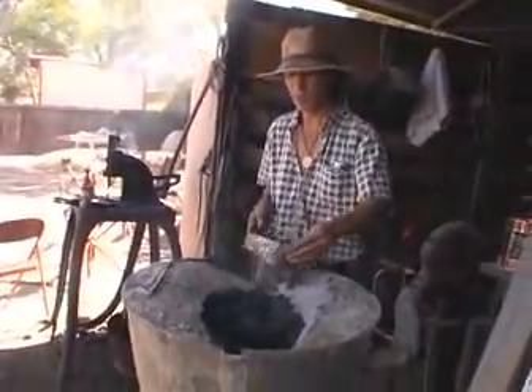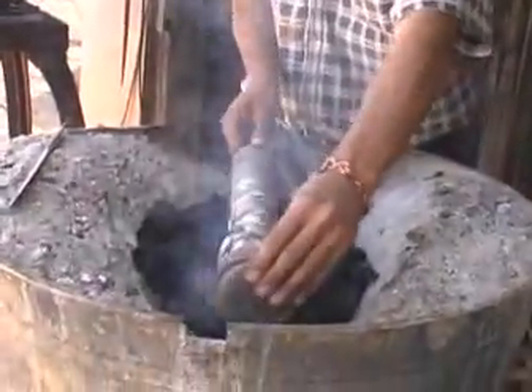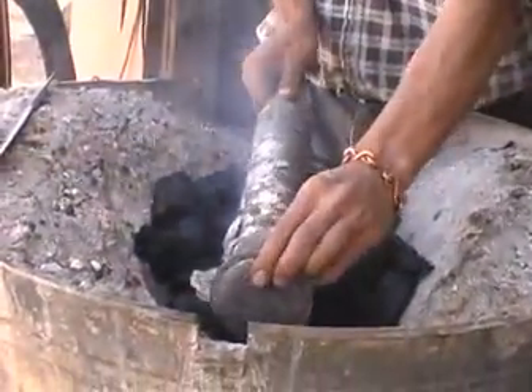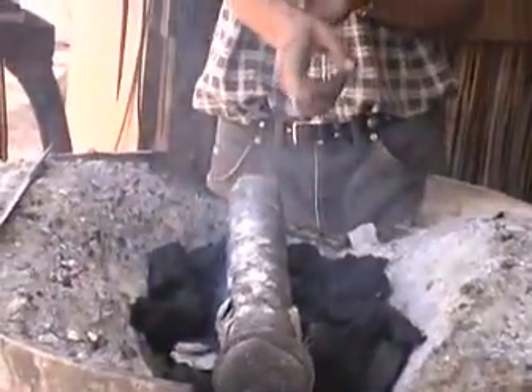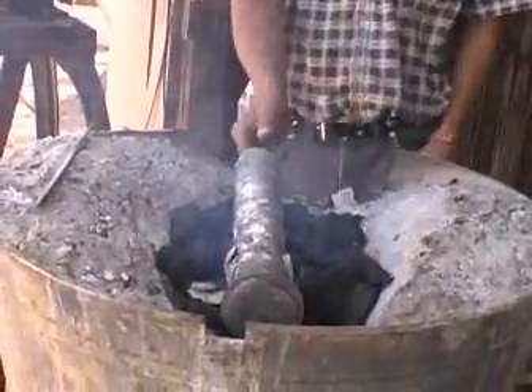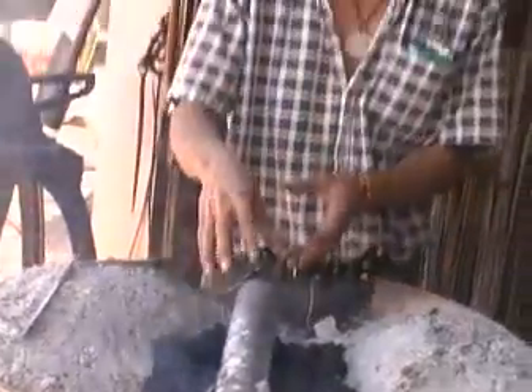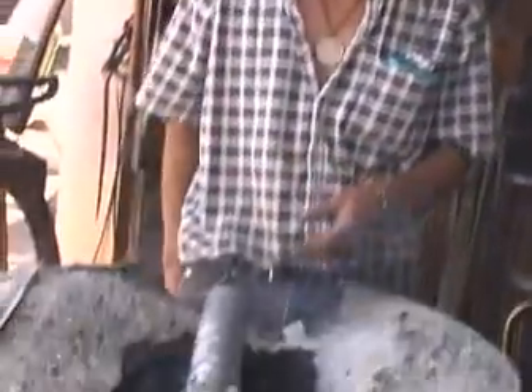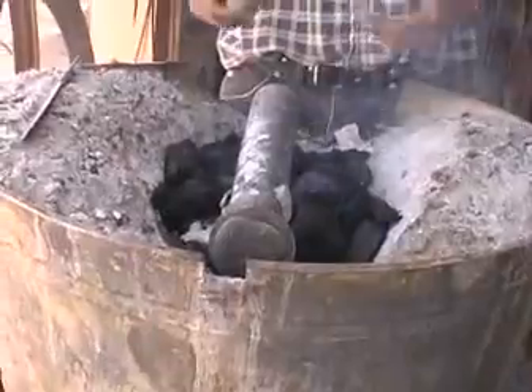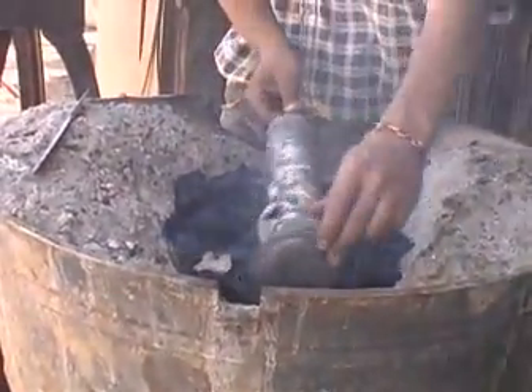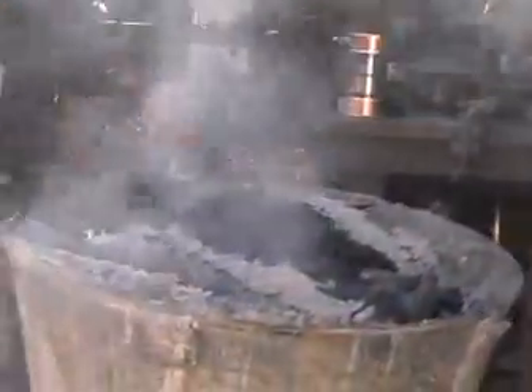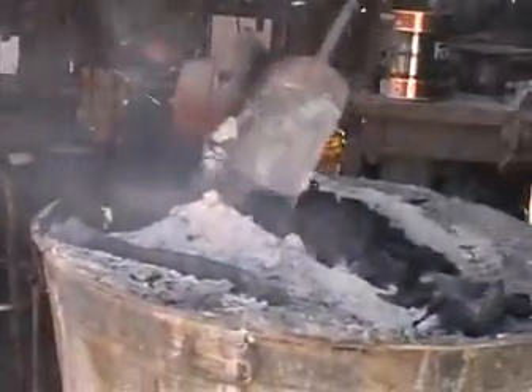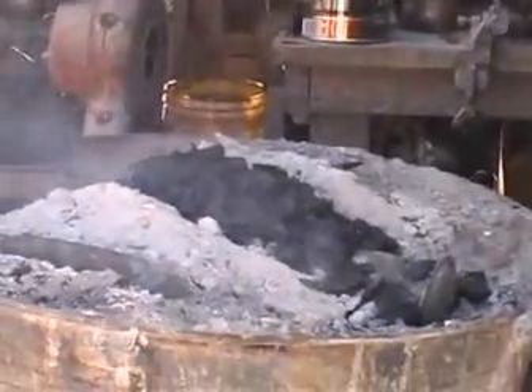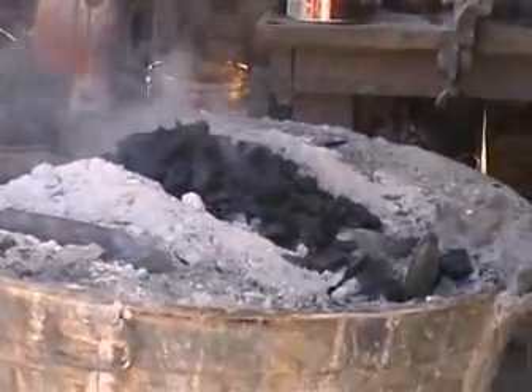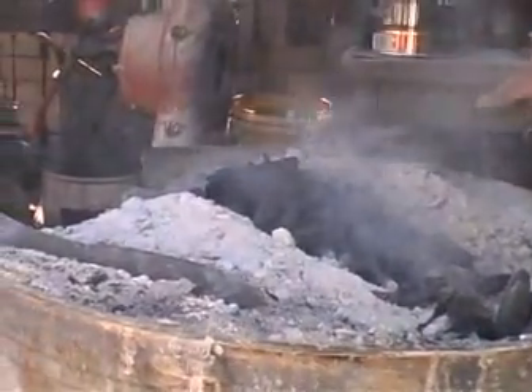Now I'm going to put this pipe on top of the charcoal here, and the whole pipe will heat up, and that will give me a cavity to put the blade into to heat it up when I harden it. The pipe also will help distribute the heat more evenly and keep oxygen and oxidation away from the blade itself. I'm just banking this fire with ash a little bit. Get a nice even heat on that pipe.